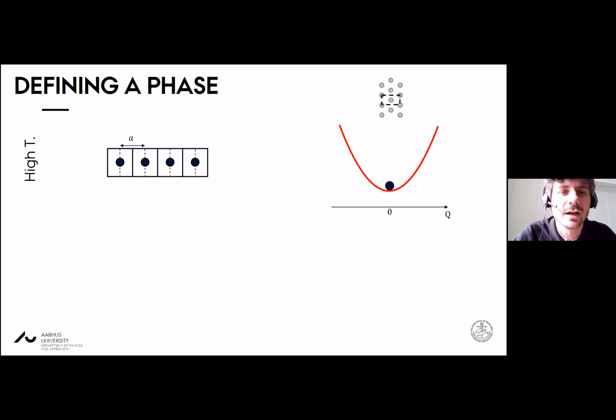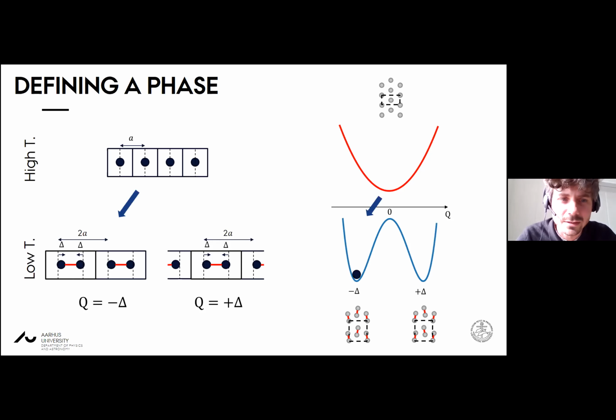which are equally spaced in the high temperature phase. And when the system cools down, there is a dimerization, which causes a symmetry breaking. And the system has to choose how it dimerizes. So it can either dimerize with pairs forming starting on this unit cell, or it can start with a pair forming in the next half unit cell over. Okay, so this dimerization would be characterized by a distortion delta. And this delta has a phase, plus or minus, depending on which one of the twins it chooses.